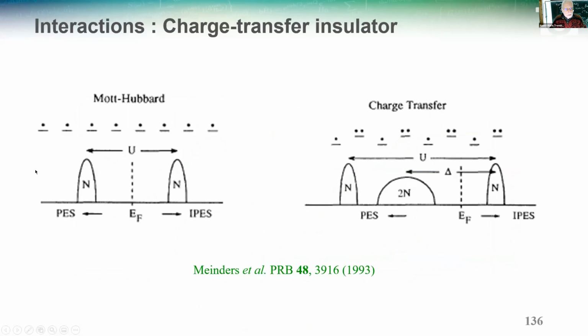Now, this was the cartoon for the Mott-Hubbard insulator, but what we really have is a charge transfer insulator. In other words, this so-called lower Hubbard band and upper Hubbard band have mostly copper character, but in between there is oxygen. And you can see what epsilon P minus epsilon D means here also, as far as again in this cartoon.